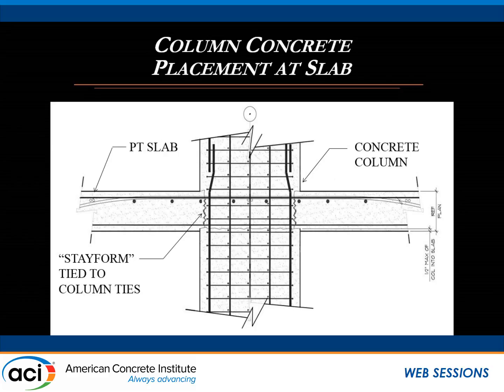But you see that we were pouring the slabs and the columns almost the same day, and they're stressing on the third day. So it was not an issue to keep an exposed cable in that little gap, because a lot of times I pour the column the same day that I pour the slab. I'll show you some slides on that. So that helped quite a bit. The contractor loves it. He didn't have to puddle, and it gave us what we need in that sandwich of the slab.